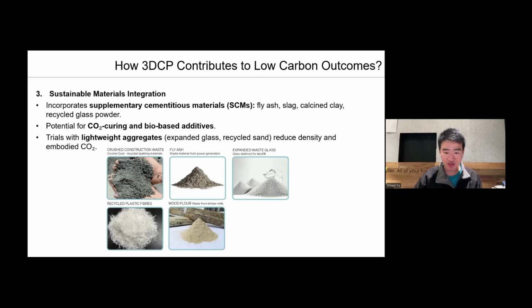We have also tested lightweight aggregates such as expanded glass and recycled sand. These help lower the density of the concrete we use and reduce the embodied carbon dioxide. Finally, we use fibers to control shrinkage and improve tensile strength. What's interesting is that because of the extrusion process, the fibers tend to align with the printing path, which can actually improve the performance compared to traditional cast concrete.